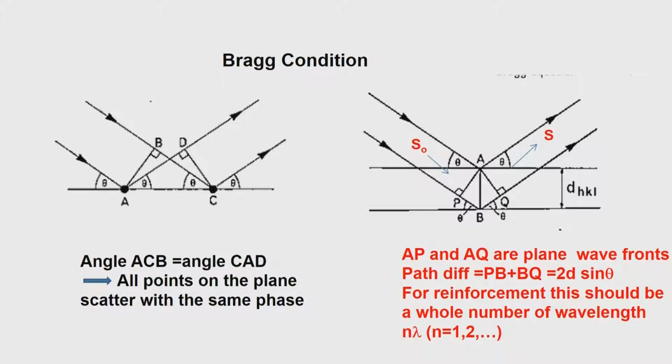any plane, there may be several atoms sitting. This is again taking you back to the bread analogy, where we take a slice out, there may be several pieces of different things which we have added in the piece of bread, and therefore, different electron densities associated with different atoms may coincide with that particular plane. All these now will scatter with a single phase, and this is a very important phenomenon, because then we need not worry about what the contents of that plane are as far as phase determination is concerned.